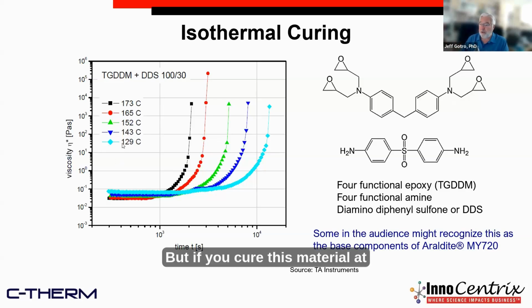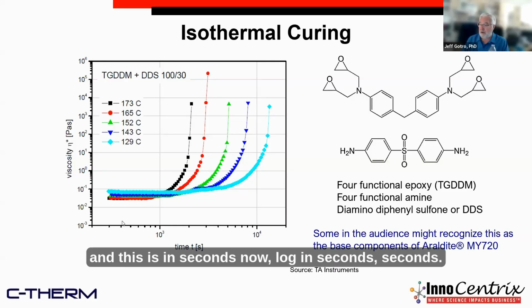But if you cure this material at 129 C isothermally, so you just put this in a process where the temperature is constant, you can see that the viscosity stays low for a while, but then it rises dramatically. Remember I told you that you're getting branching and the molecular weight is increasing, but when all those chains start to connect or cross-link, the viscosity goes up very, very quickly. You can see on all these different curves at different temperatures, you have different amounts of time, and this is log in seconds.